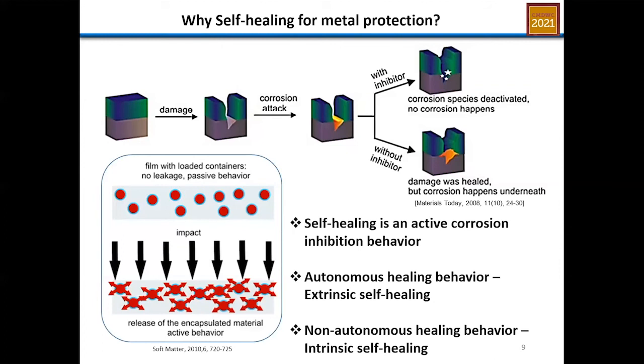So in a paper that was published in Soft Matter in 2010, it was clearly explained that the encapsulated materials are loaded in such a way that there is no leakage. It provides a passive behavior when it's not damaged. But once there is an impact that results in a damage, there is a release of the encapsulated material.